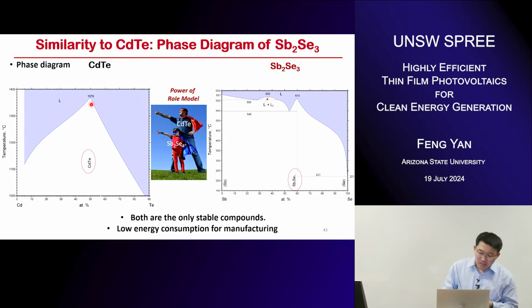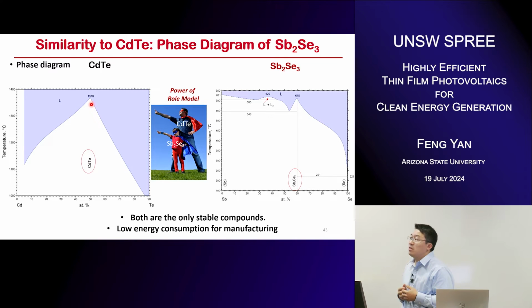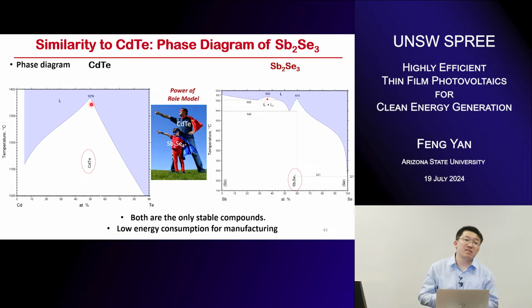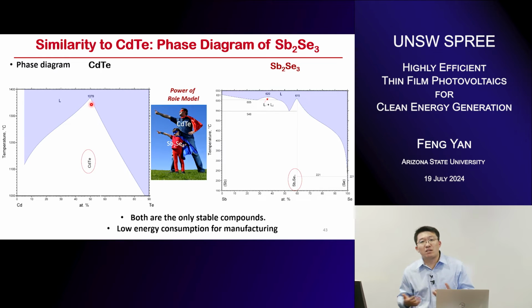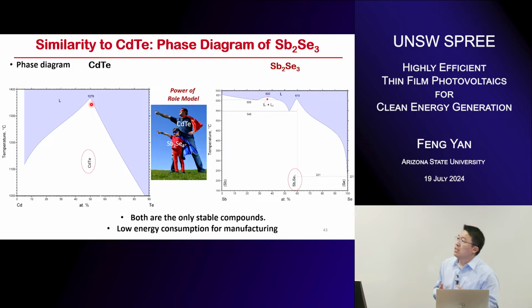So the manufacturing costs a lot of energy, because you need to vaporize all of this compound at a high temperature. But for the antimony selenide, the good thing is that it's pretty stable, also the only compound between the antimony and the selenium. And it has a relatively lower melting point, just around half that of the cadmium telluride. That means we can use a very low manufacturing temperature to vaporize this compound.